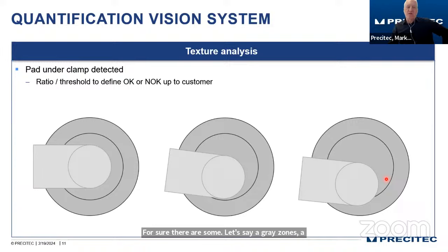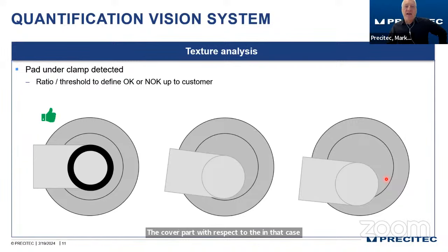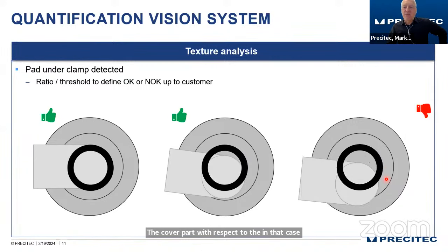Typically it's not always 100% aligned, the cover part with respect to the, in that case, cylindrical cell. So if it's completely out of range, we can easily stop the process or not perform the weld, and just bring that information out to the customer that there is something wrong with the clamping or with the position of the contact, and that can be corrected afterwards.